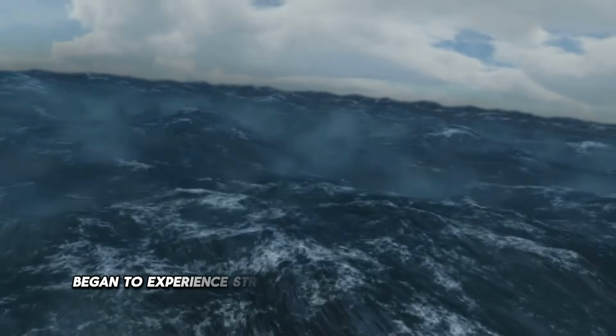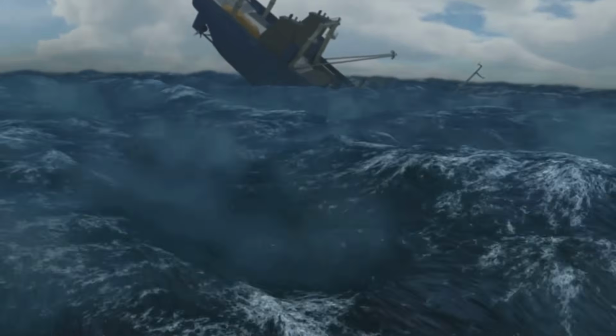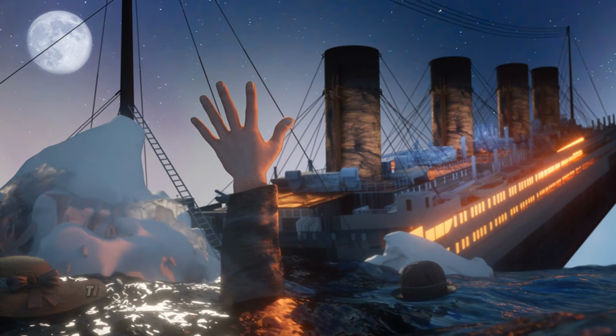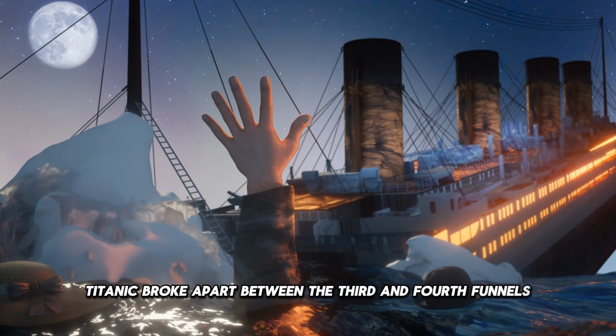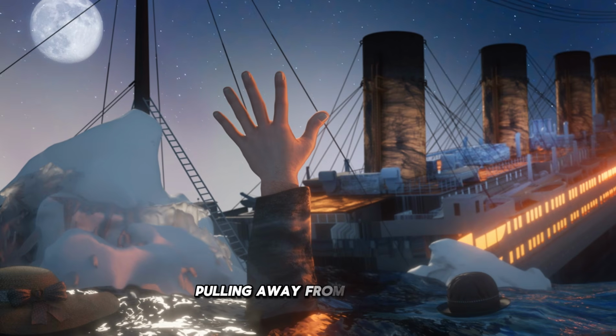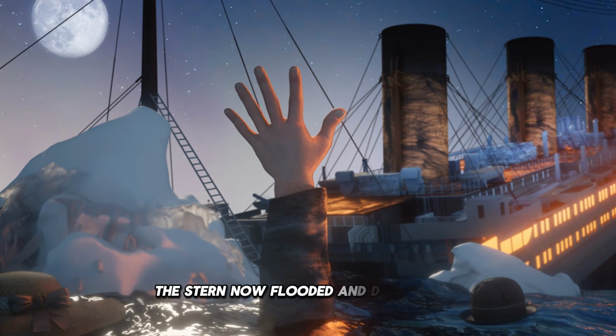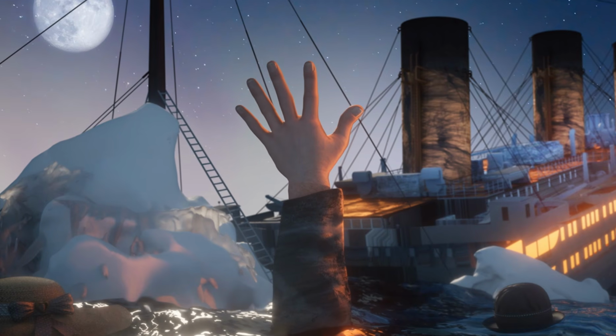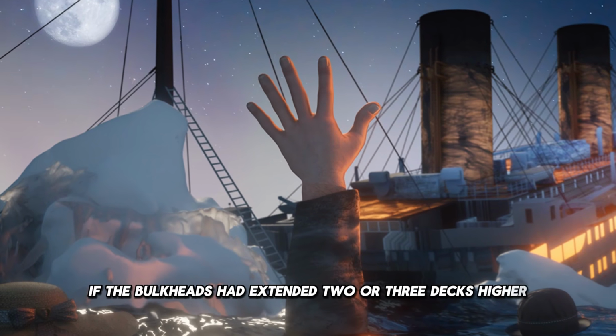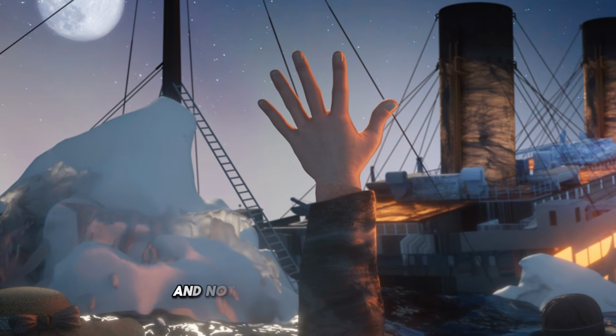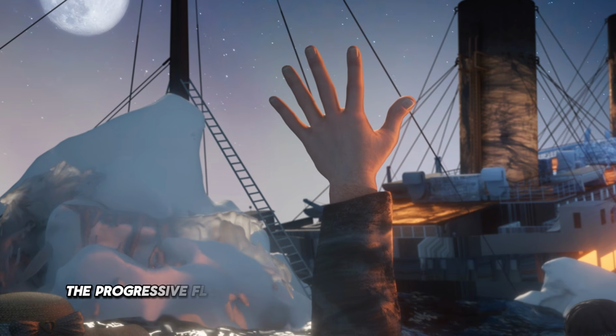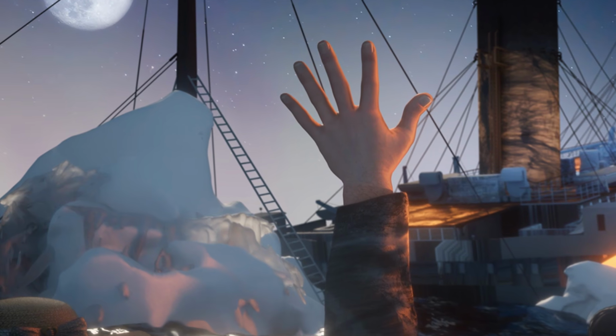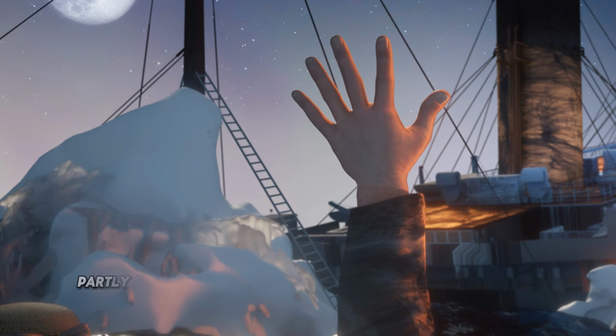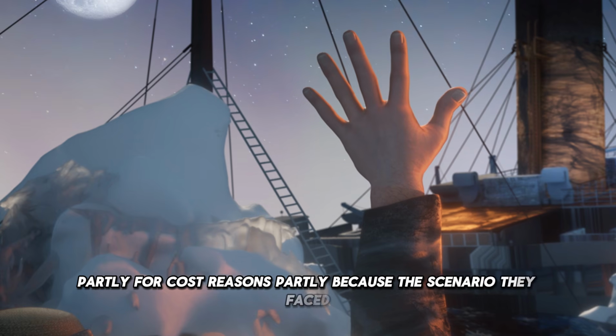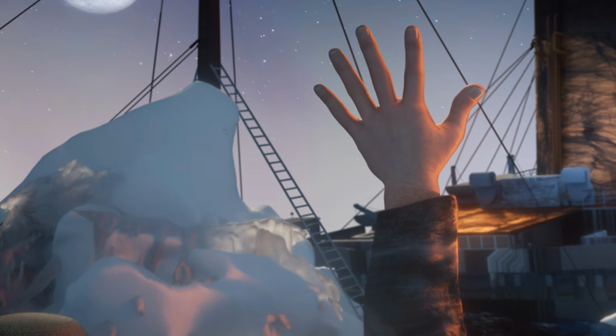The hull, now unsupported in its midsection, began to experience structural stress far beyond its design limits. At approximately 2:17 a.m., Titanic broke apart between the third and fourth funnels. The bow section sank first, pulling away from the stern. The stern, now flooded and destabilized, sank minutes later. If the bulkheads had extended 2 or 3 decks higher, a modification that was technically feasible and not extraordinarily expensive, the progressive flooding scenario might have been survivable. The designers chose not to extend them, partly for cost reasons, partly because the scenario they faced was considered beyond the design envelope. It wasn't.